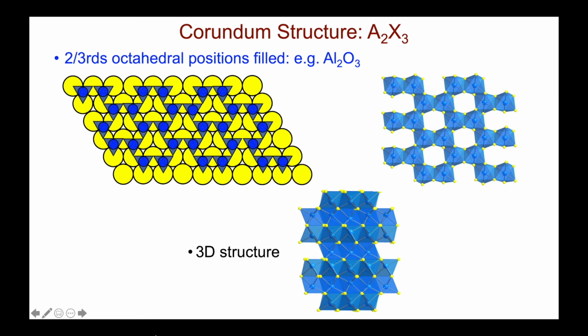As it turns out in alumina, there is some face sharing of the octahedra, and if we look very closely at this picture, we'll see the signs of that, and a phenomenon I mentioned earlier, that when 2 octahedra share their faces, the cations, to minimize their repulsions, will move off center and just displace a little bit. And hopefully that's evident to you in this picture. This aluminum has moved down a little bit. It's lengthened these 3 oxygen bonds and shortened these. This one has done the opposite, and we've been able to at least maximize the separation between these 2 aluminum cations to minimize their repulsions.